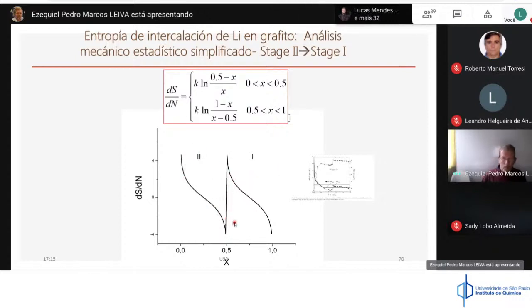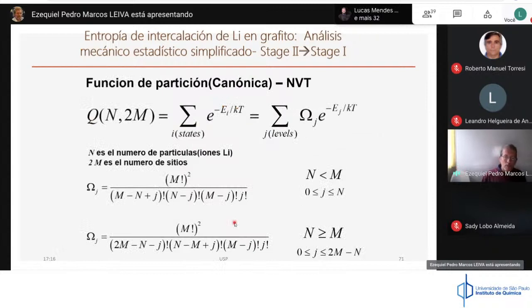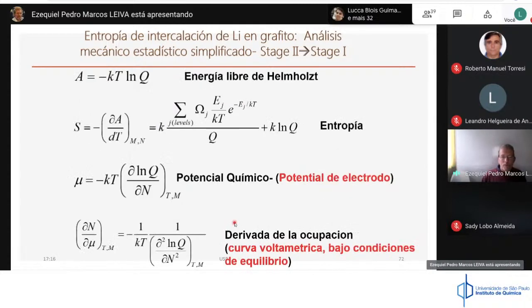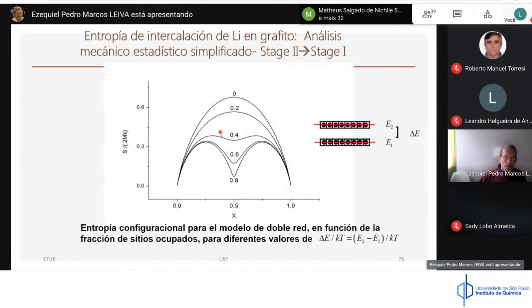Of course, you can take the previous simple model and calculate the properties by ordinary statistical mechanics, where you can calculate the free energy, the entropy, or the chemical potential from the partition function. That is the old-fashioned statistical mechanics way, and you can get the entropy as a function of the configuration. And you can see that if you have, instead of one single lattice, you have this maximum entropy at 1/2. If you have this system, you have the minimum in the entropy in this way.